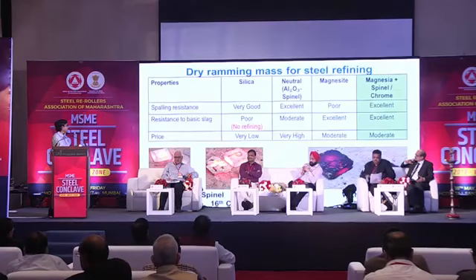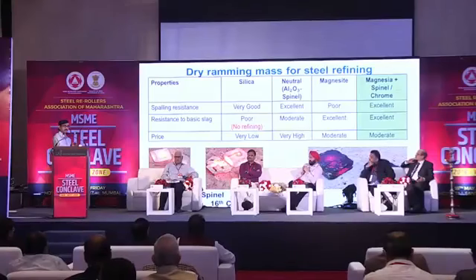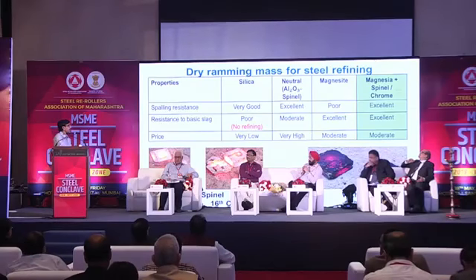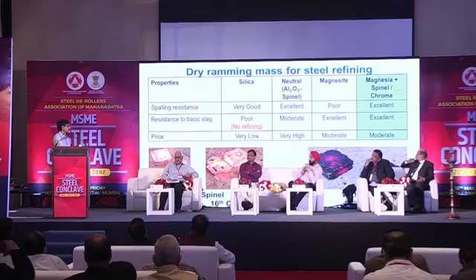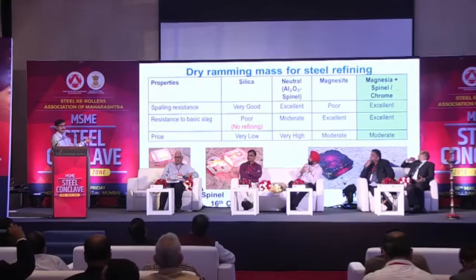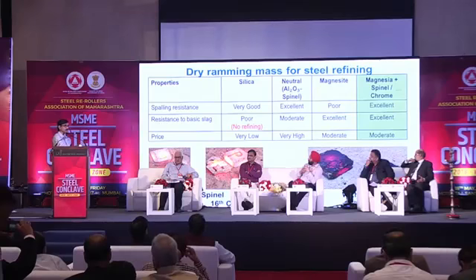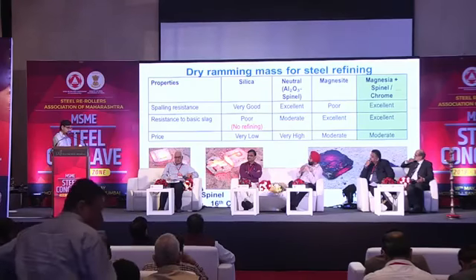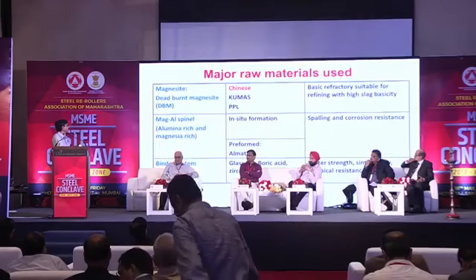You see that silica ramming mass may not be suitable for refining, though the cost is low. There is neutral ramming mass available in the market, mainly the alumina spinel type, but the cost is very high. Our target was to develop a magnesite-based basic ramming mass, but the problem is that the spalling or thermal shock resistance is poor, so you have to improve it. We use some spinel or chrome in the batch to improve its thermal shock resistance. I think you cannot see the bottom picture, but whenever you use some spinel, you can improve the thermal shock resistance, as you can see from the picture.